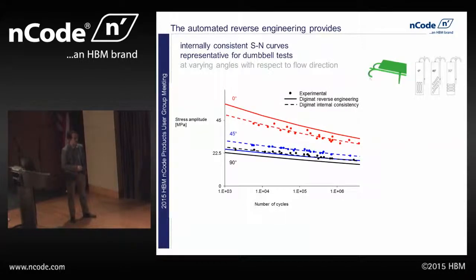And then we can go ahead and use that model and reapply it to the microstructure that we're seeing inside of those individual dumbbells to see if we can predict the fatigue life of the dumbbells. And you see that for these, it's basically the same orientation state with 3 different loadings. We're able to get a very nice correlation there. So that gives us a good indication that we should see good correlation at the part level.